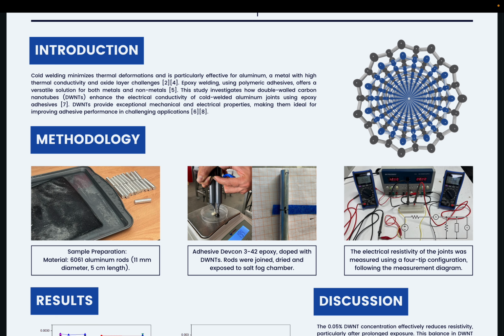After applying the adhesive, the samples were left to dry at room temperature for 36 hours, and then they were exposed to a salt chamber in accordance with the ASTM B117 standards at intervals of 0, 4, 7, and 14 days. The electrical resistivity of the joints was measured using a 4-point probe method, which allowed us to accurately assess the resistivity while minimizing the effects of contact resistance.